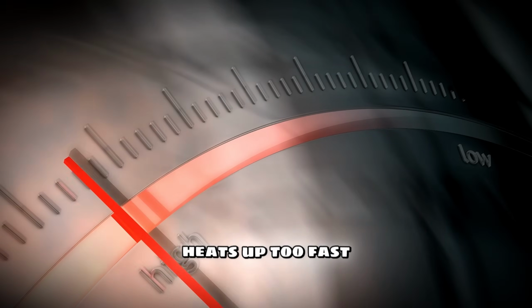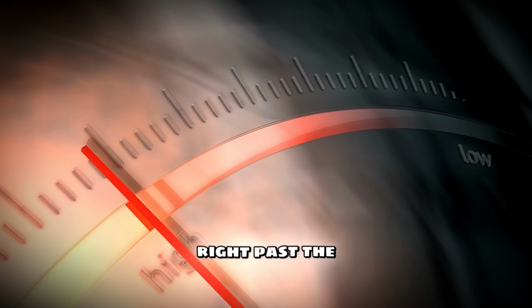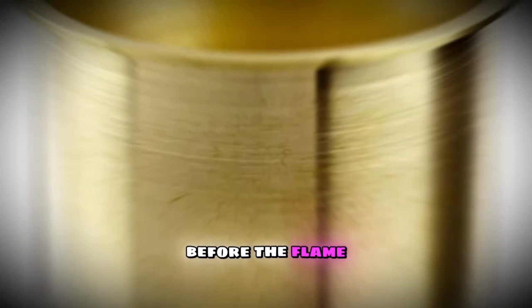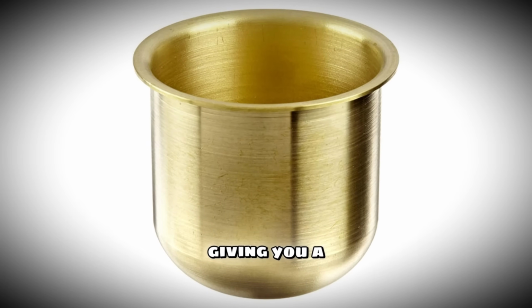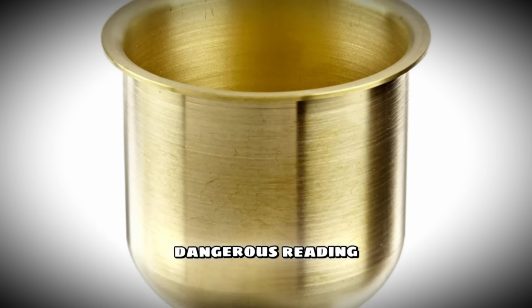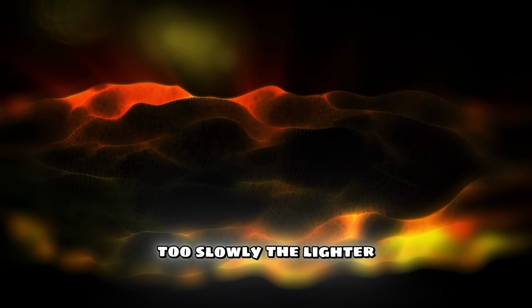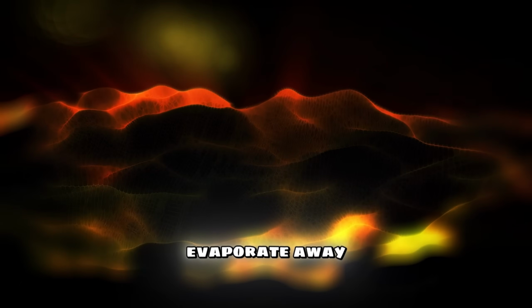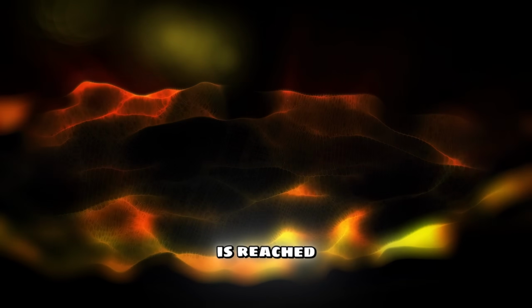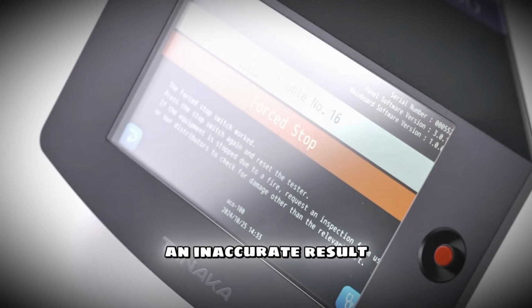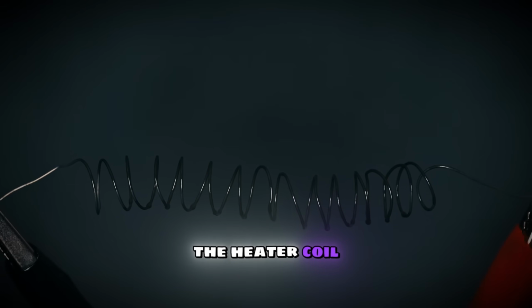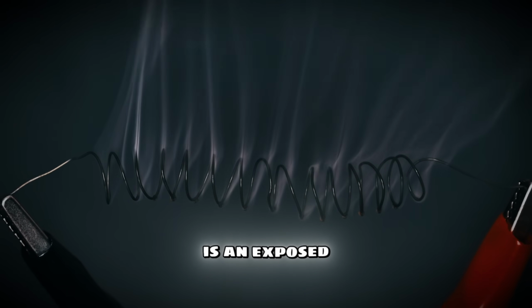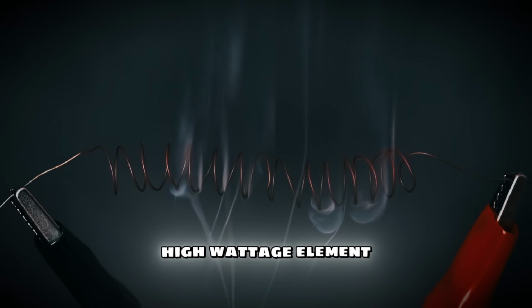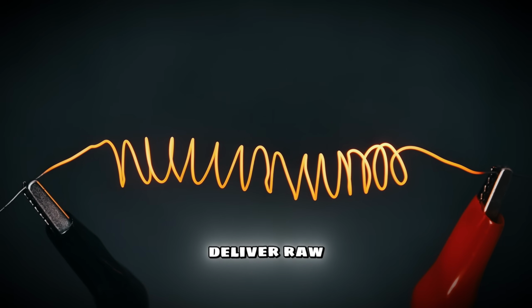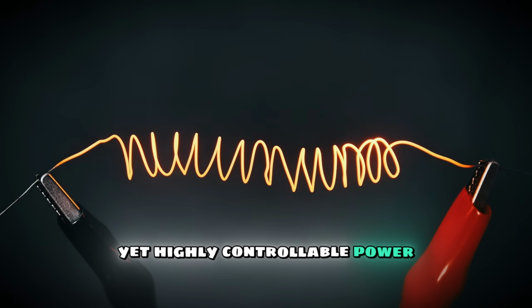If the asphalt heats up too fast, you will blast right past the flash point before the flame sweeps across the cup, giving you a falsely high and dangerous reading. If it heats too slowly, the lighter volatile compounds might evaporate away before the flash point is reached, again giving you an inaccurate result. The heater coil for the Cleveland flash tester is an exposed high wattage element designed specifically to deliver raw, yet highly controllable power.